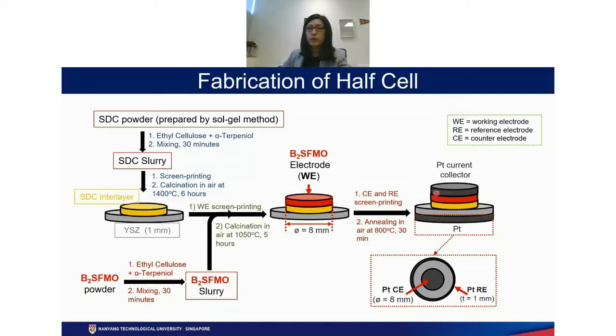And then we also put the platinum current collector on top of the B2SFMO, and also the platinum as a counter electrode, and also the ring reference electrodes, made by platinum. And then we go ahead and characterize it.